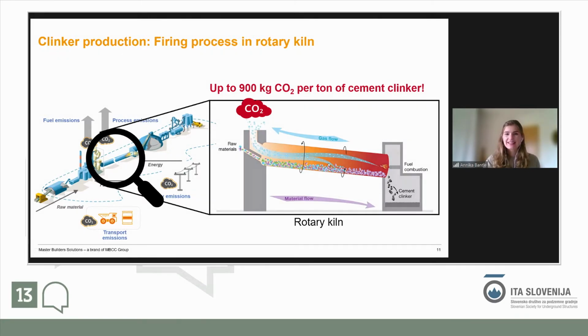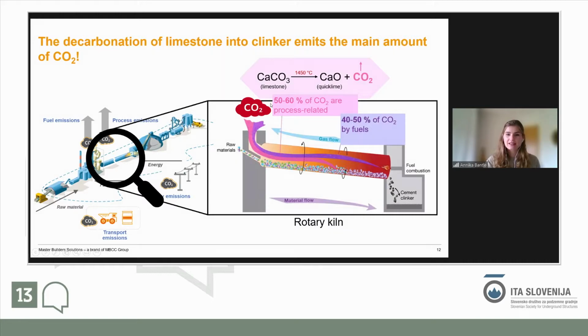And why is that? Here you see in the next slide that within this process of the rotary kiln, 50 to 60% of the CO2 is process related, and 40 to 50% originates from the fuels that you use to heat up the system. And the chemical reaction behind this, you can see it up here in pink. So basically the calcium carbonate limestone is heated up to 1450 degrees to have the chemical reaction, the decarbonation of the limestone to calcium oxide, which is also better known as quicklime, and CO2.